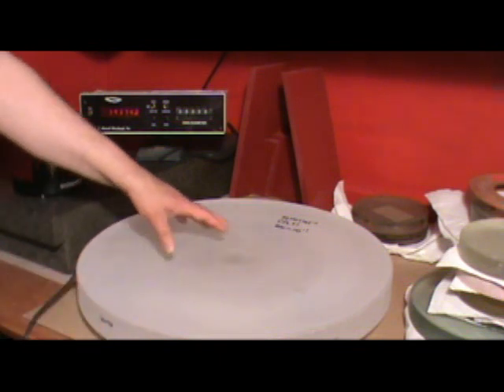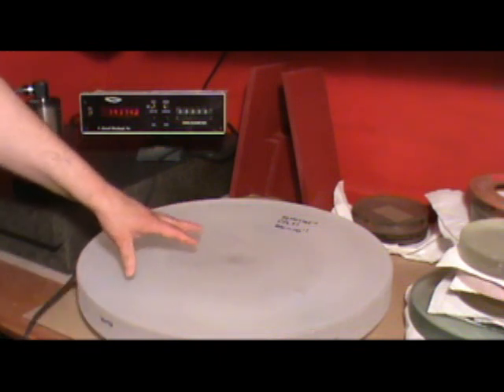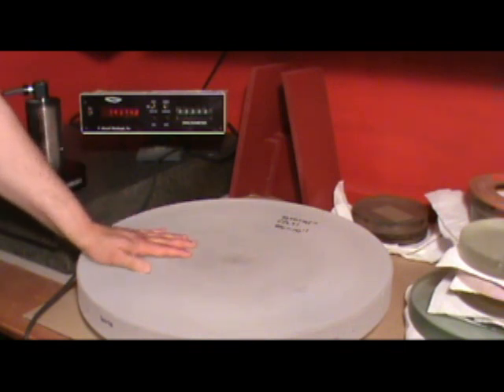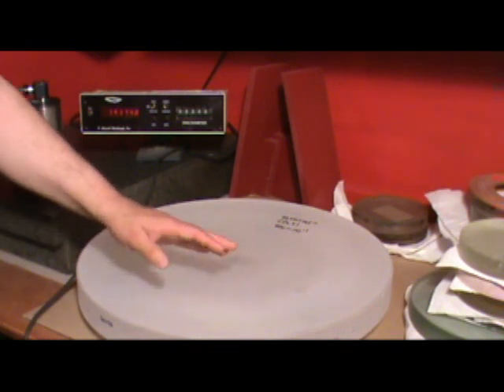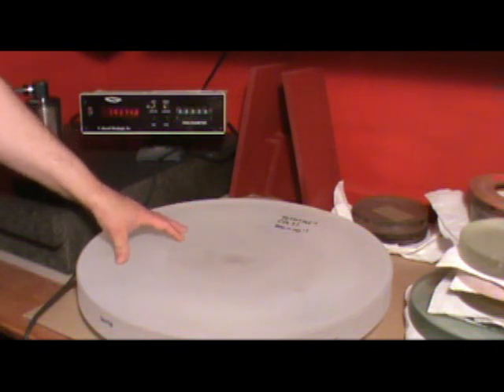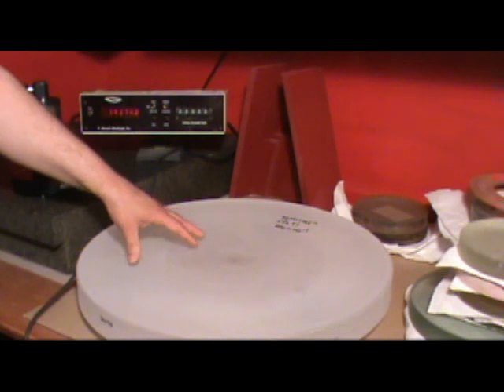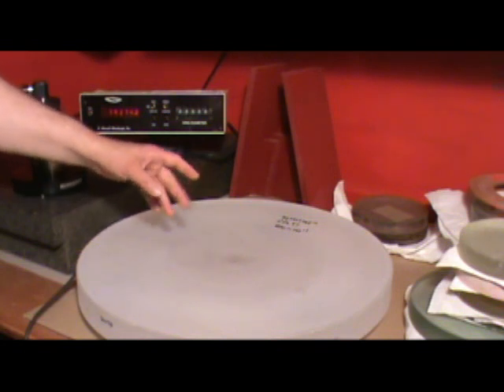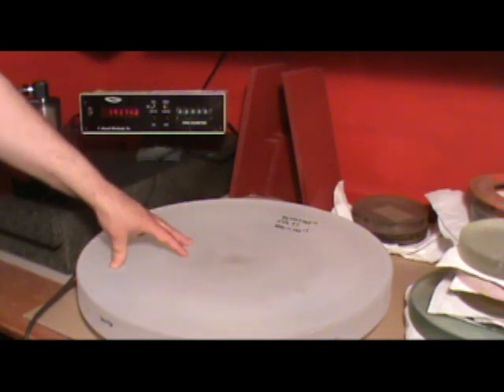Now, again, during generation, the reason you have to look at this is that I have a target that I'm shooting for. With this mirror, it's f3.5, which would be a radius of curvature of about 140 inches. When you have a mirror generated for you, normally you're within 6 to 10 inches of that range, but they might be off as much as 20 inches.